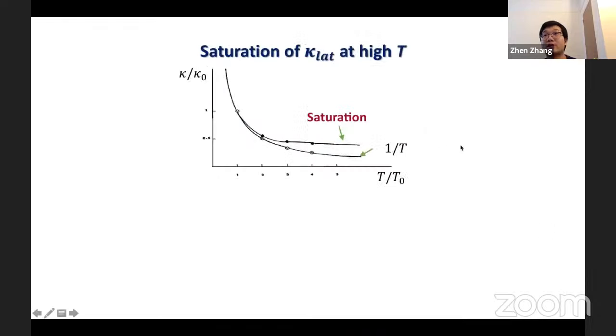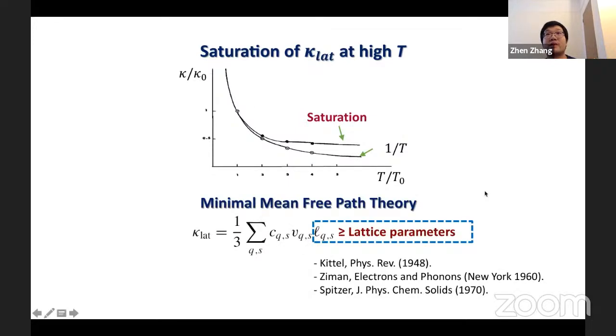So renormalized frequencies can be used for accurate free energy calculations, while the phonon lifetimes can be used to calculate mean free path and lattice thermal conductivity. In terms of phonon mean free path and lattice thermal conductivity, the minimal mean free path is a phenomenological explanation of the saturation behavior of kappa at high temperatures, but lacks rigorous proof. It claims that a phonon should propagate at least an interatomic distance or a smallest crystal lattice parameter. Therefore, at high temperatures, this saturation of mean free path leads to a higher kappa than the theoretically expected 1/T